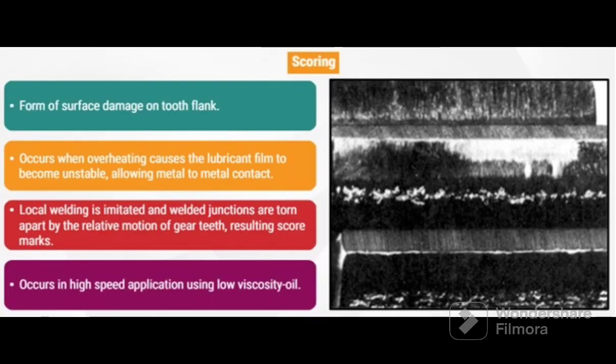Scoring. It is a form of surface damage on tooth flank which occurs when overheating causes the lubricant film to become unstable, allowing metal to metal contact. Local welding is initiated and welded junctions are torn apart by the relative motion of gear teeth, resulting in score marks. Generally, this type of failure occurs in high-speed application using low-viscosity oil.